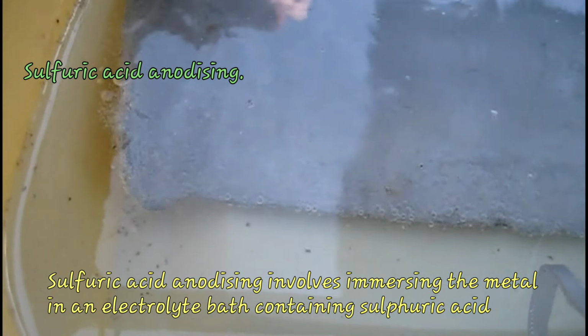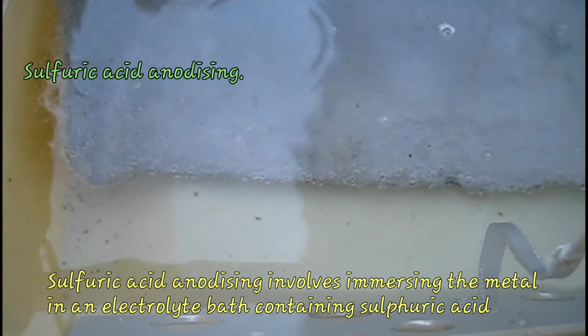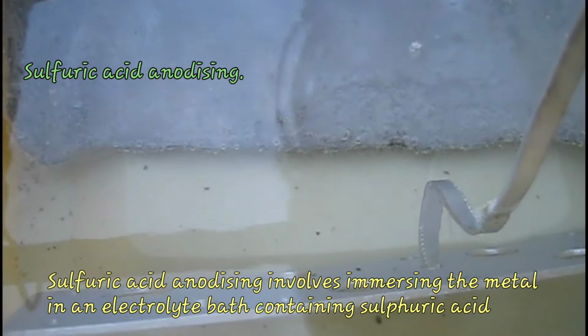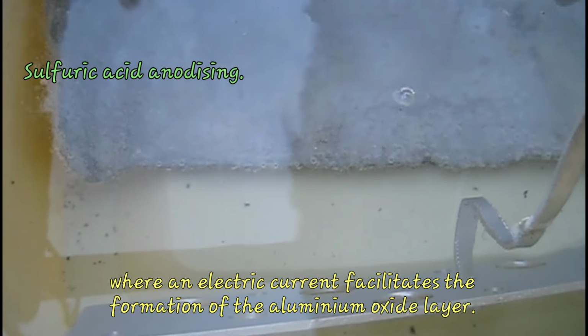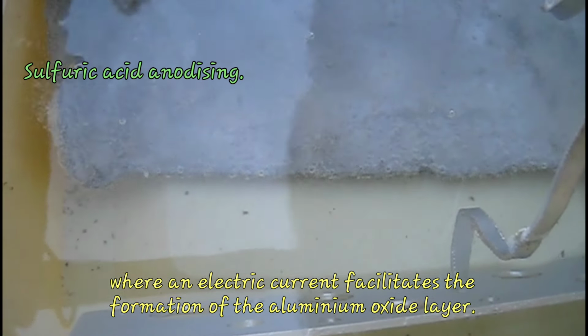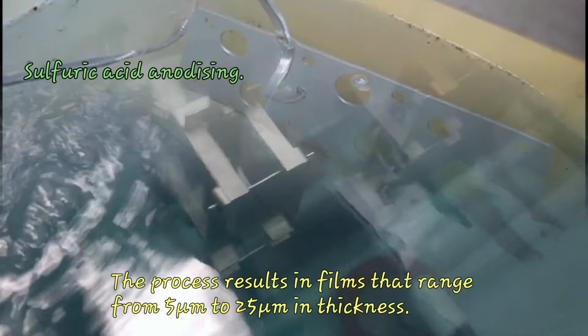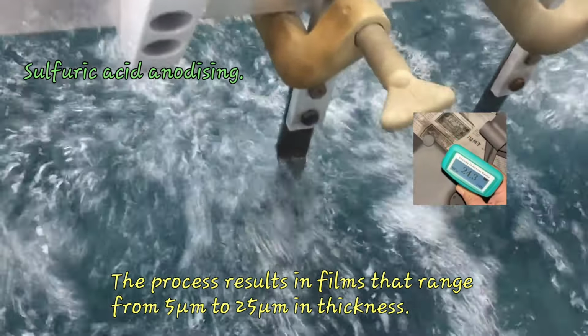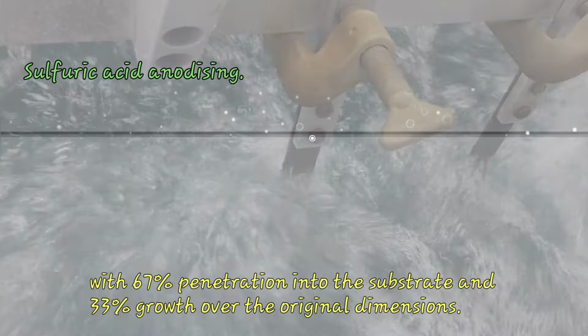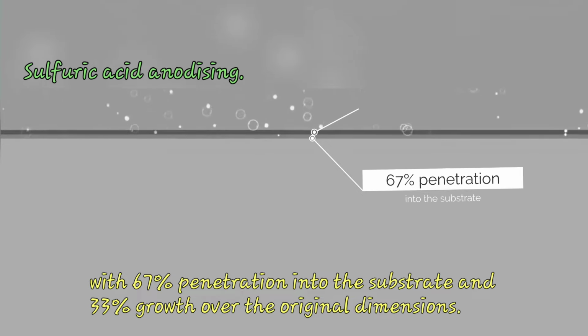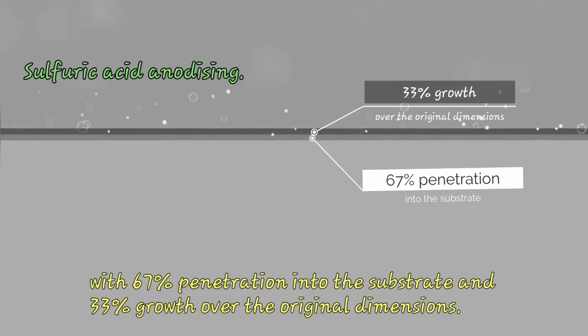Sulfuric acid anodizing involves immersing the metal in an electrolyte bath containing sulfuric acid, where an electric current facilitates the formation of the aluminium oxide layer. The process results in films that range from 5 micrometers to 25 micrometers in thickness, with 67% penetration into the substrate and 33% growth over the original dimensions.